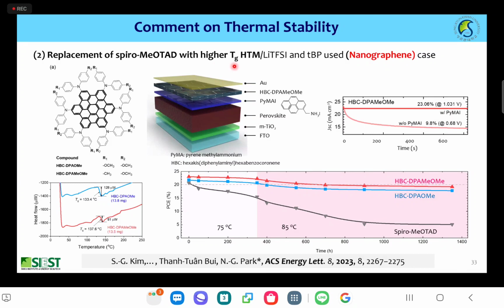Also, recently a higher glass transition temperature HTM, the nanographene, the structure looks like this one, was developed. If you use this material without some interface layer, the initial efficiency is okay, but with time the efficiency drops a lot. Therefore, we use this interlayer. The crystal structure looks like the nanographene, and we found that the MPP tracking shows very stable output of this perovskite solar cell. And we also proved the 85 degrees C stability of using this nanographene material.